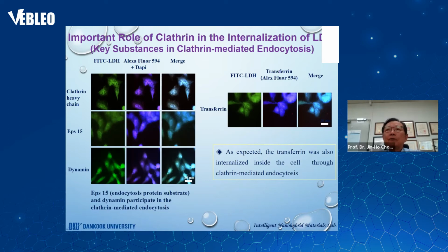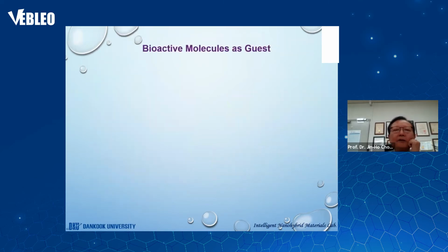As a positive control, we also compared internalization of FITC-LDH with that of transferrin, which is well known to undergo clathrin-mediated endocytosis through the transferrin receptor, as I mentioned just before. Intracellular FITC-LDH was highly co-localized with the transferrin labeled with Alexa Fluor 594. This is well consistent with the results seen for clathrin, dynamin, and EPS15, confirming the clathrin-mediated internalization of LDH nanoparticles. So we were able to reconfirm that our inorganic particles could be internalized inside the cell through clathrin-mediated endocytosis.